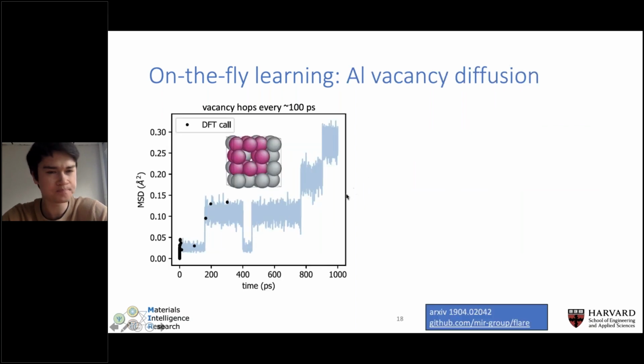So that's aluminum, and we can slowly dial up the complexity of these systems. Here I'm taking that aluminum supercell and removing 1 atom to create a vacancy. We wanted to see, are we able to properly model vacancy diffusion? Again, we start with an empty training set, and we have a bunch of DFT calls initially as the model uncertainty is quite high. And after that initial period of DFT calls, the model takes over.